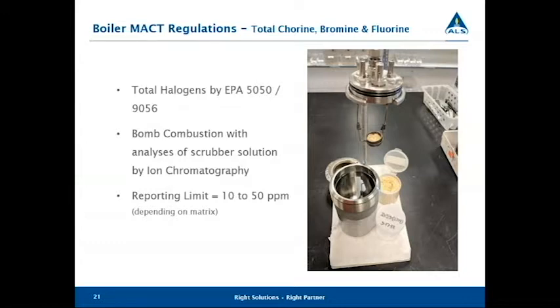And then after a set time, we release the pressure, collect the scrubber solution, and then analyze it by ion chromatography. And we can get reporting limits down into the 10 to 50 ppm range. I'm currently looking at an automated system for this, which involves a pyrolysis furnace, and then we'll have an automatic scrubber solution system that is analyzed by IC.